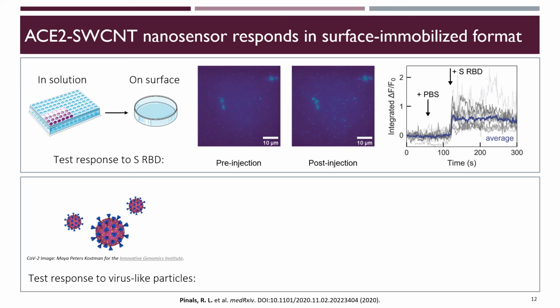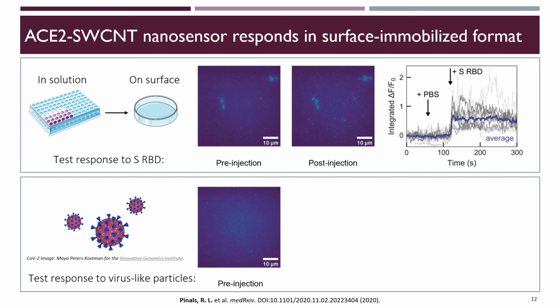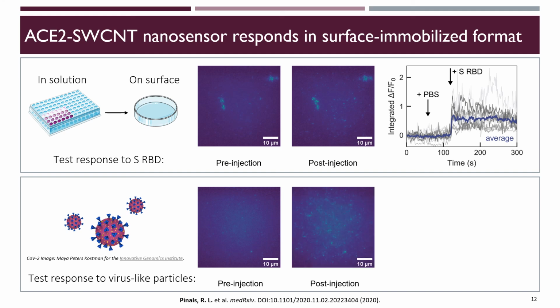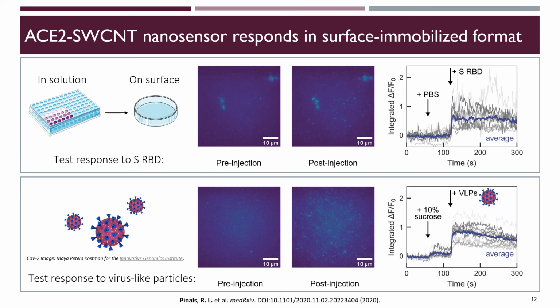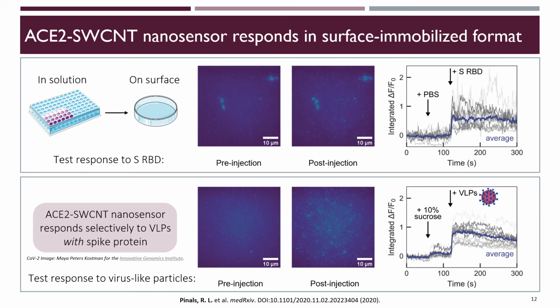And even more excitingly, we were able to test these nanosensor constructs with virus-like particles sourced from our collaborators. And our nanosensors show this robust over 70% increase in fluorescence. As a control, we found that using virus-like particles that do not have the spike protein only resulted in a 20% change in fluorescence, thus confirming the specific spike ACE2 interactions responsible for the sensor response.